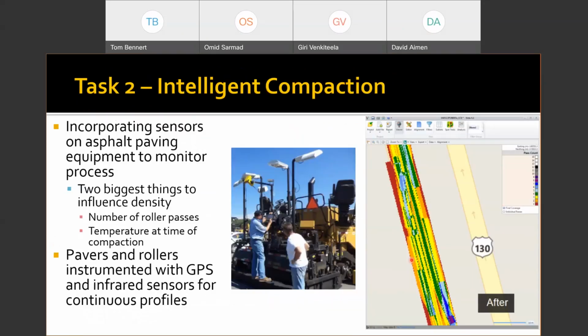Other work that we've done, and I don't know how many people have heard about intelligent compaction, is that we're putting a bunch of sensors on the back of a paver and our rollers to get an idea of what the temperature is. So here's an IR gun. We're looking at an infrared image of the temperature of the pavement as we're placing and compacting it. We also have GPS sensors on this equipment so we can get an idea of the number of passes, where that roller has been. If we can get even coverage, good even density, then we should be able to get better and longer lasting pavements.